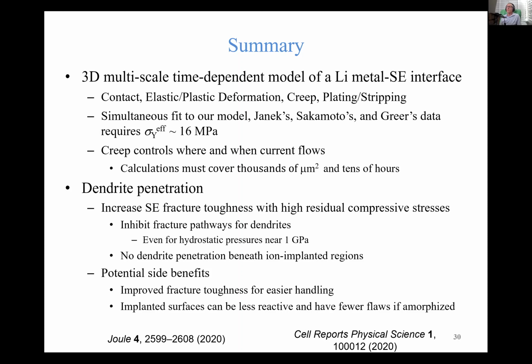Even if you build up hydrostatic pressures within the lithium that's close to a gigapascal, which is possible with modest overpotentials, with realistic overpotentials, even those kinds of pressures can be overwhelmed by residual compressive stresses that you can impose. And the evidence we have so far is that we see no dendrite penetration beneath ion implanted regions. In addition to reducing dendrite penetration, there are other potential side benefits for introducing high residual compressive stress.